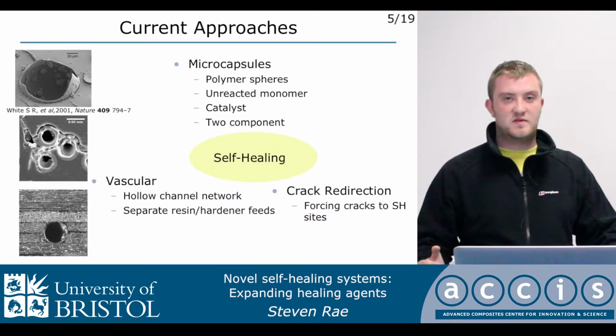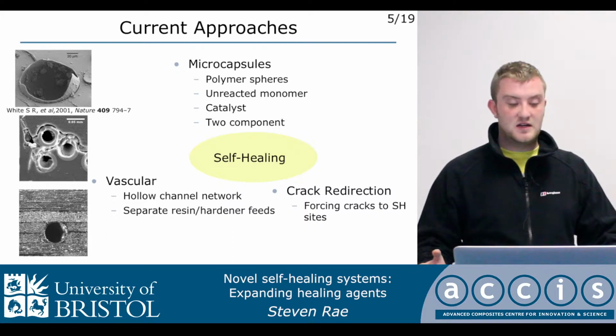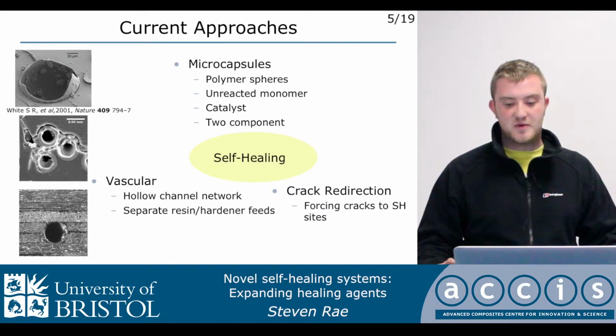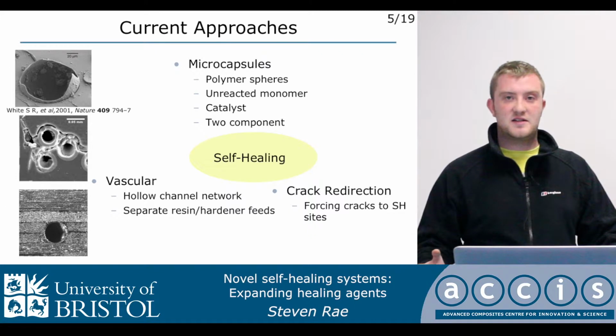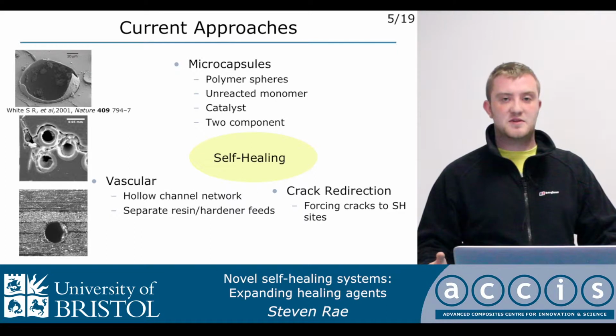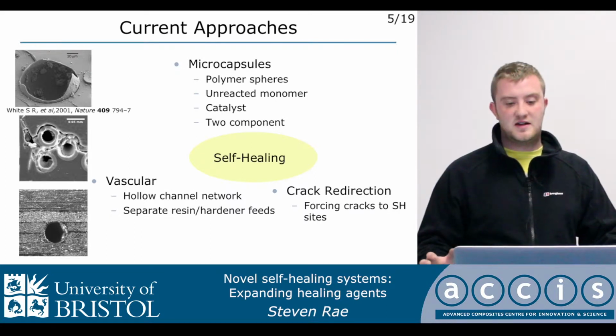So the current approaches that we're investigating at Bristol for self-healing take two forms: microcapsule systems, whereby microcapsule spheres are dispersed in the matrix, and when an impact event occurs, they're ruptured, releasing the unreacted monomer, and this comes into contact with a catalyst in the matrix, thus curing. Or we can have a two-component microcapsule system where the two components mix and then heal. The other system we look at is a vascular system, which has a network of channels where we can pump the healing resin into the damaged area, thus healing it.